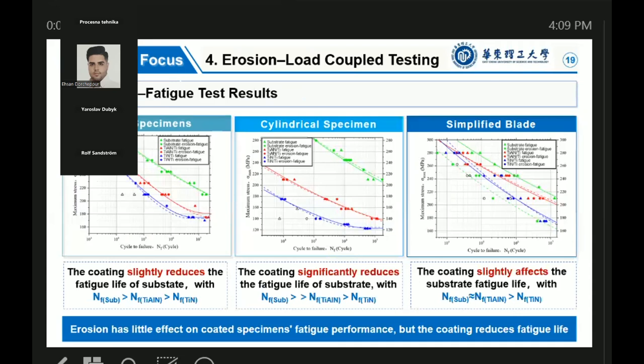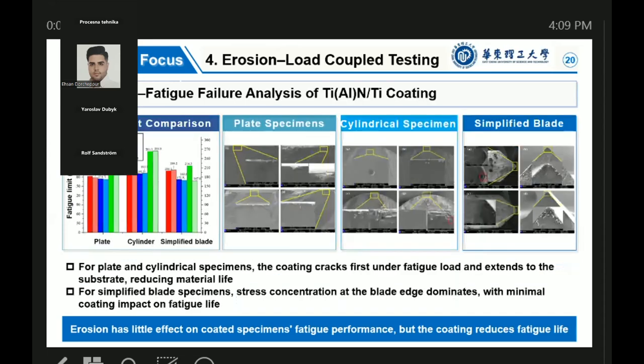Under erosion-fatigue coupling, we compared the results from pure fatigue and the coupled test. As long as the coating was not fully penetrated, erosion had little effect on fatigue life. However, the coating itself slightly reduced the overall fatigue life, likely due to stress concentration at the coating cracks. The comparison of fatigue limits confirmed this also. Fatigue fracture surface analysis showed that for plate and cylindrical specimens, fatigue cracks mostly initiate from the coating, reducing fatigue life. For simplified blades, cracks always started at the blade edge, indicating geometry-driven stress concentration.